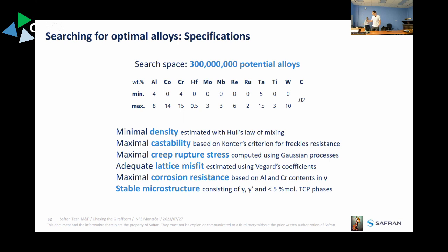So once we have the model, we have the composition dependence and we can screen large spaces, and that's what we did there. You have the boundary of each element there. They are very broad for nickel-based alloys, and the step that we defined for each of these elements defined a space of about 300 million alloys, and we had a bunch of criteria. These two were from CALPHAD calculations. This one was from the regression model. And then the last three were just rule of mixtures or empirical models that we could find in other papers.